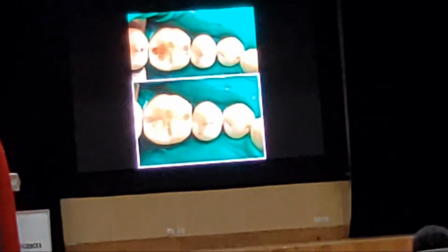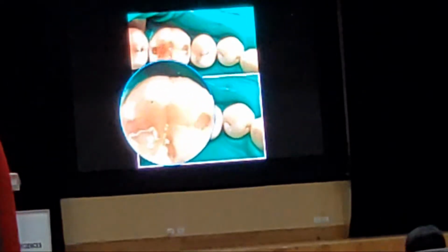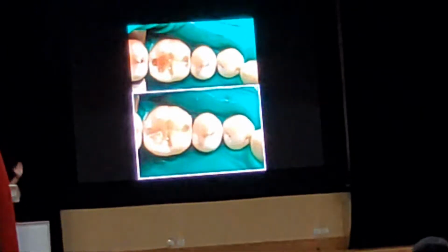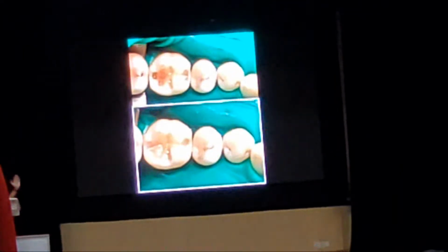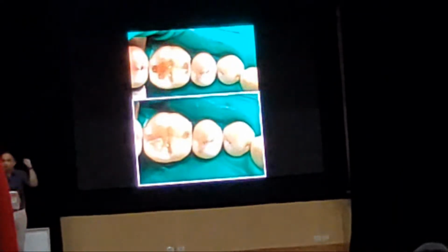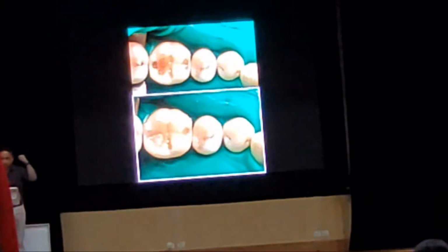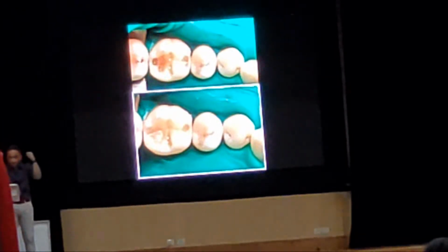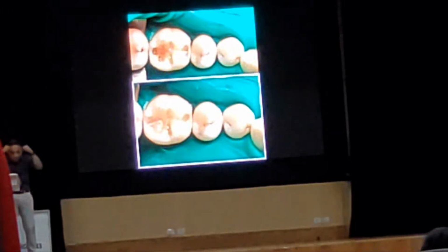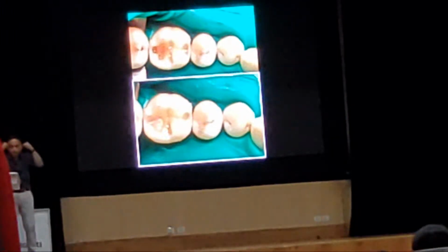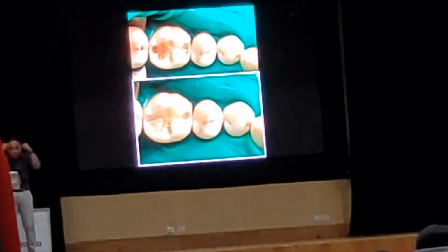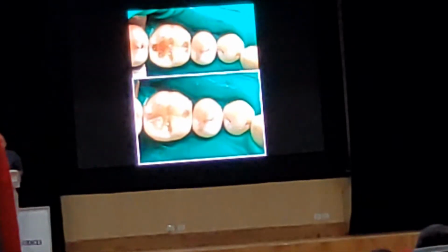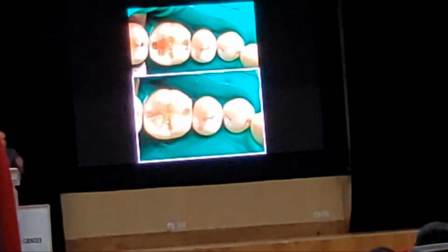So in this case, please never ever connect the walls. When you place composite, do wall by wall. Take your time. Take a small volume of composite. The moment you connect two walls with composite, high C factor, when you light cure, resin will shrink. So what will the composite do? It will pull the buccal and the lingual walls to the center like this. This is called cuspal strain. Correct? It will break the bond. There will be marginal gap. And now this patient goes home and he will call you that I have sensitivity on mastication. That's because there is cuspal strain.